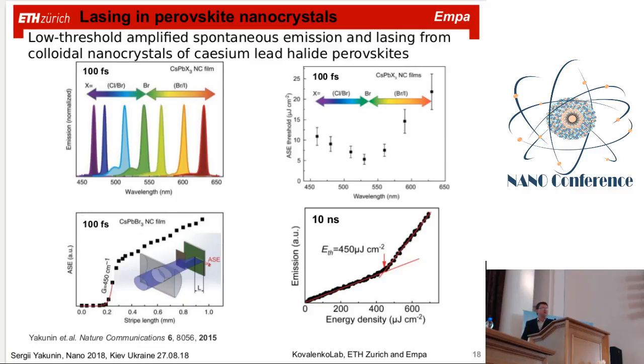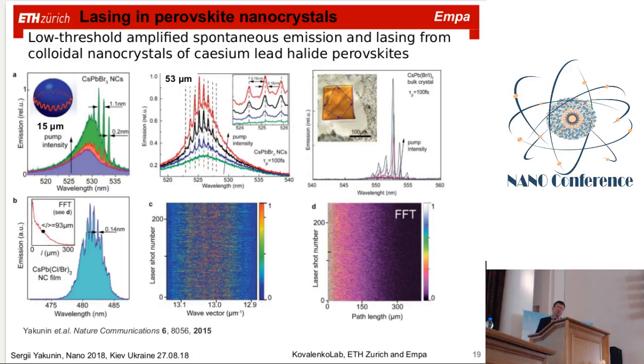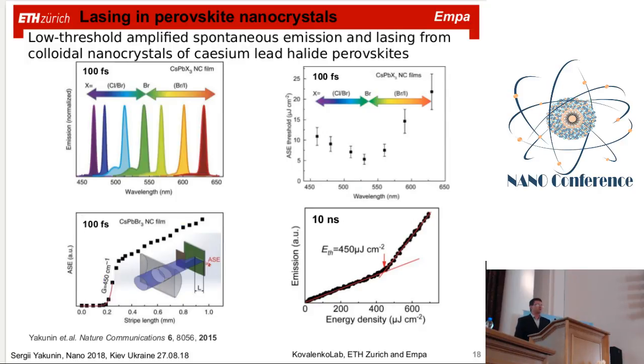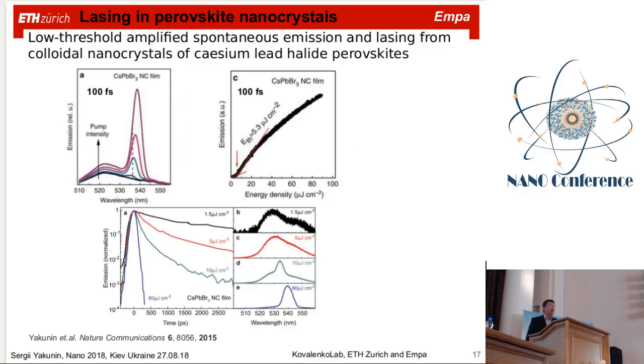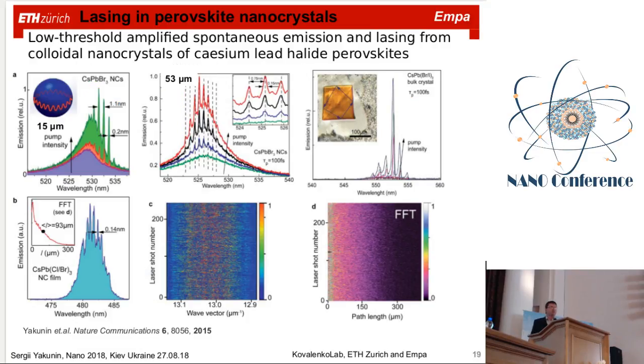And then we also tried to go further. First we started with very short excitation pulses in the femtosecond range, and then we tried longer excitation pulses, trying to reach a continuous or quasi-continuous wave range, which is highly demanded now in order to get low-threshold or thresholdless lasers. And we reached 10 nanoseconds, which is already longer than the build-up time of amplified spontaneous emission. It shows that in principle we already worked in a quasi-continuous amplification regime.